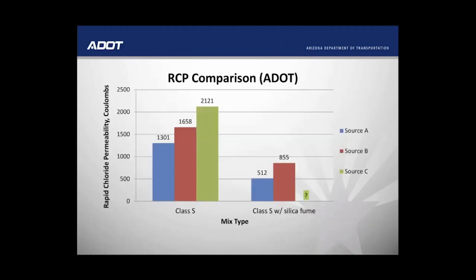If we compare the chloride permeability of our typical Class S mixtures to those with silica fume, the reduction is quite apparent. Here we have mixtures produced with three different aggregate sources, and you can see the reduction in permeability from the low to moderate range to very low, except for source C, from which a silica fume mix has not yet been produced for ADOT.